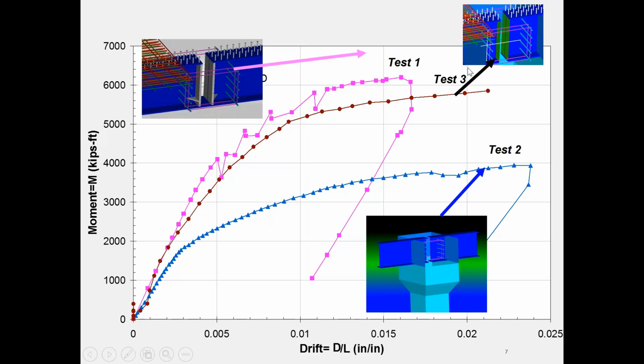Now, when you put the end plate, that end plate also helps to distribute the load. So you don't have all the compressive force being transferred only through the bottom flange, but this end plate also helps. So it's an intermediate solution between this case and full continuity between bottom flange. Now, also related to this, some people say, okay, we don't do anything in the case of the pre-stressed concrete girder, so why don't we see that? Well, in the case of the pre-stressed concrete girder, first of all, you have a very large area of a bottom flange that is bearing in the concrete, and the modulus of elasticity of the concrete and the concrete diaphragm is about the same, so you don't have that problem. But in the case of the steel, we will.